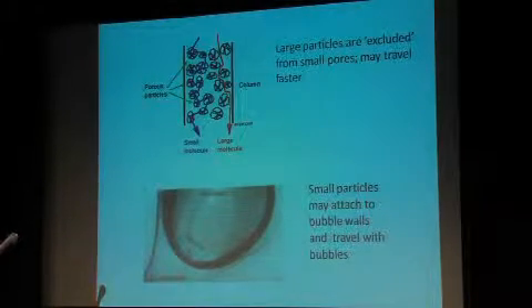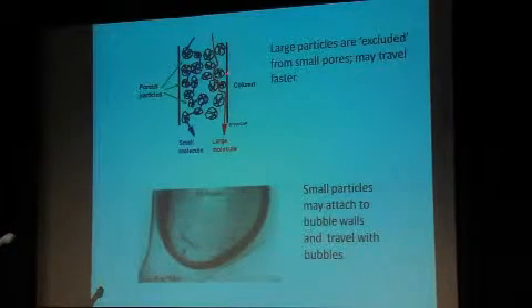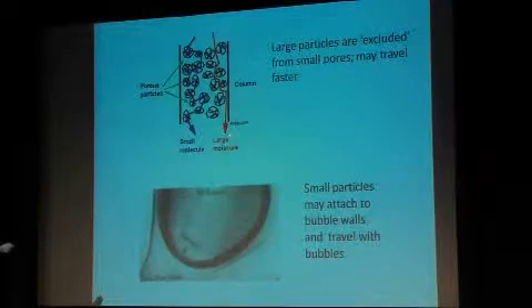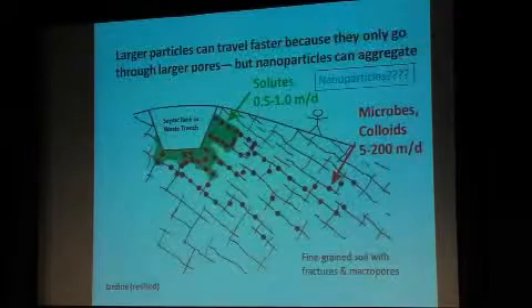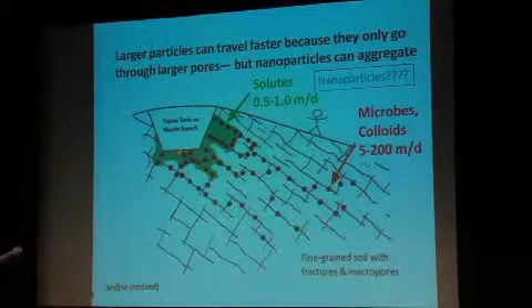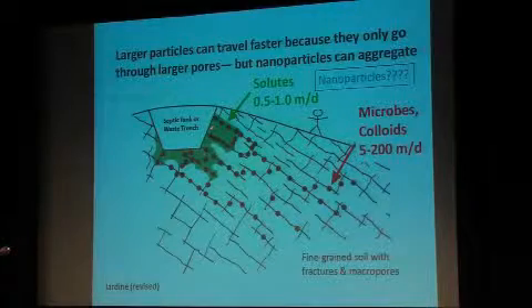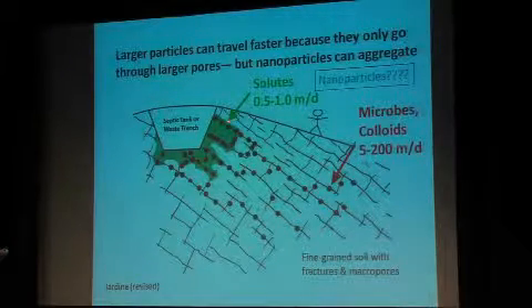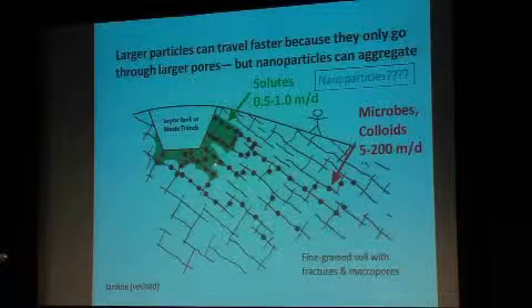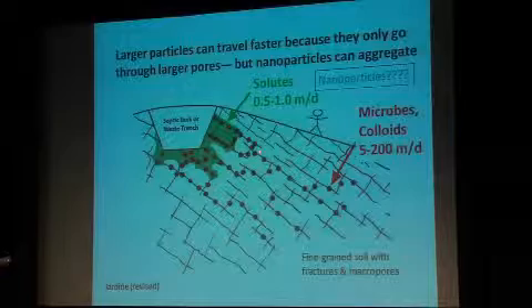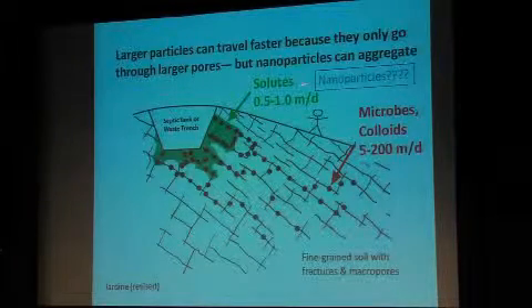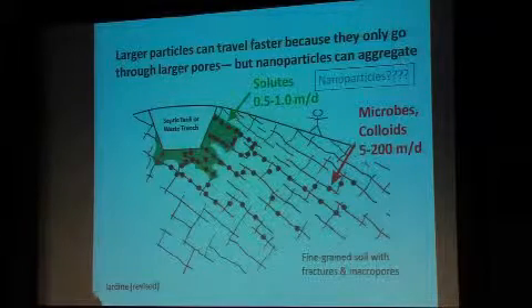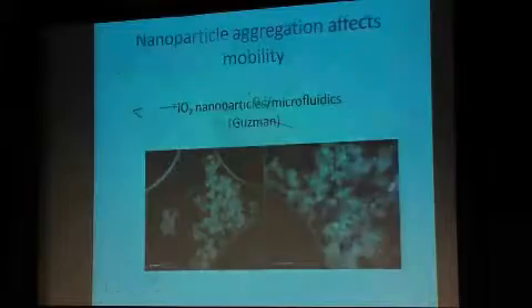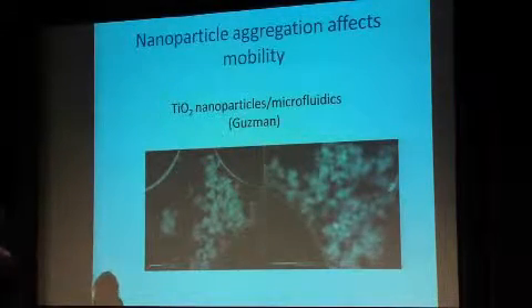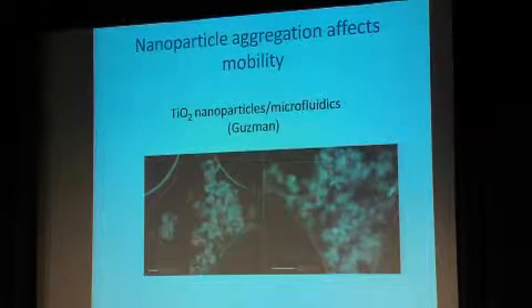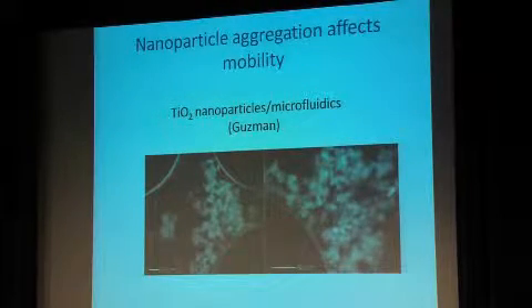Small particles can take very tortuous routes through little pores. Big particles can go only through the larger ones. They can't go through those little pores. That can affect how things will travel in the environment. So if you look at a septic tank leaking, the solutes often will go through a certain distance because, maybe not solutes, but really, really small particles, they go through a tortuous route. Large things like microbes or colloids take only the larger paths and they can move a lot faster. Nanoparticles may move slower or faster depending upon exactly where they can fit in the pores and also whether they aggregate or not. Because if they aggregate, they're now behaving like the larger particles, or they may be clogging pores. So we don't necessarily know how nanoparticles will move in the subsurface.